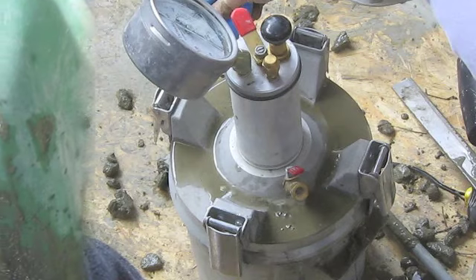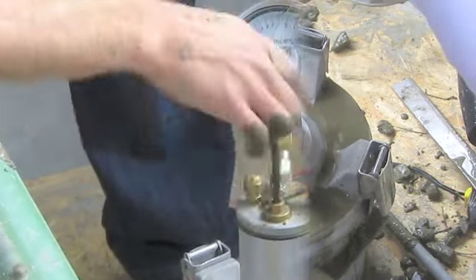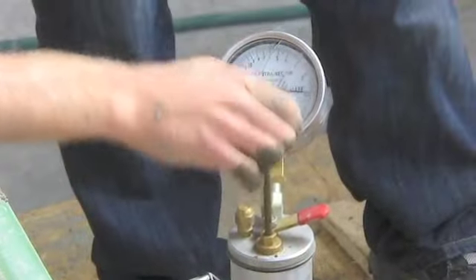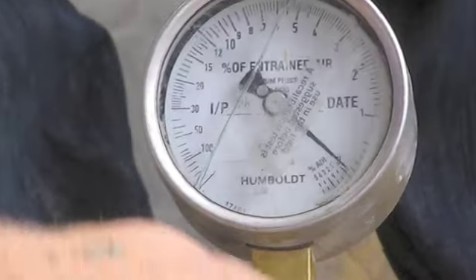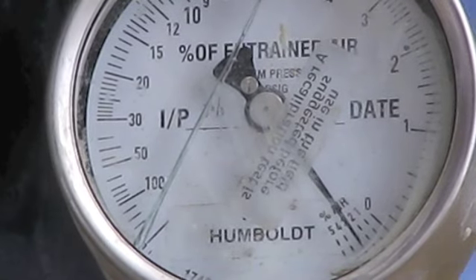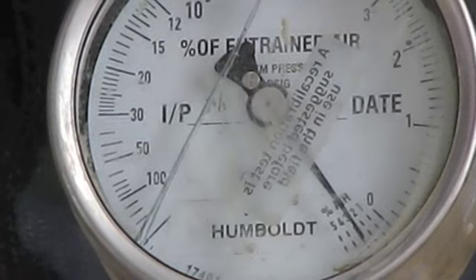Once this is complete, use the pump to pump the air pressure on the gauge to the initial pressure. Wait a few seconds for it to equalize, and then pump a few more times to make sure it's in the right location. Close both petcocks and press down on the thumb lever to release the air into the bowl. Hold down the lever for a few seconds and lightly tap the gauge with your finger to stabilize the gauge reading. The number that you see will be your air content for the concrete mix.